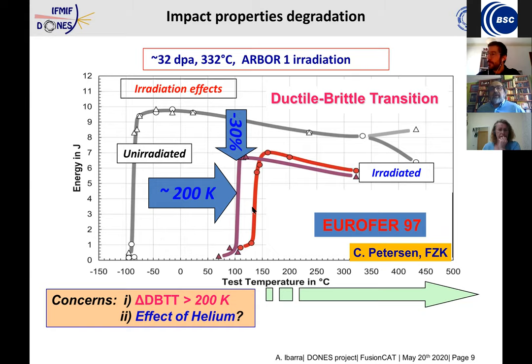There is another very important property that is very relevant when we are talking about structural materials, what we call the impact properties. There is a parameter that is very important in the design of components, the ductile-brittle transition. You know that usually when we are at very low temperatures, it is very easy to break a material. That means that it is brittle, and at high temperatures, usually the materials are much more ductile, so they are able to accommodate relevant deformations. Of course, when we are designing a component, we would like to work in an area in which they are ductile, because in that case, they are able to accommodate some change in the structure of the component or things like this.